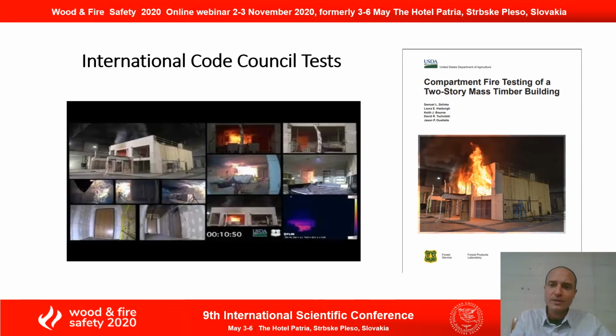These tests were performed at the Alcohol, Tobacco, Firearms and Explosives Laboratory by the Forest Products Laboratory, and these were in support of the International Code Council's ad hoc committee on tall wood buildings. We ran 5 different tests, and these had a much bigger opening factor. The compartments themselves were much bigger. In these, there was no fire regrowth observed in any situation. And we looked at 5 different scenarios: a fully encapsulated case, a partially exposed ceiling, partially exposed wall, and then 2 fully exposed compartments where the effective automatic sprinkler systems were examined.